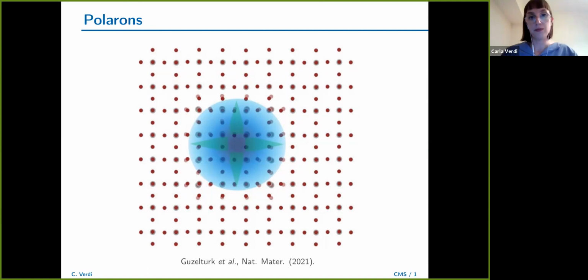Now, the properties of the crystal can be really affected by the presence of polarons. For example, there can be distortions in the crystal lattice, and the electronic properties can change dramatically. For example, the effective mass of the electrons can increase substantially. And in general, there can be a more or less large degree of localization of the electronic wave function, depending on how strong the interaction with these phonons is.